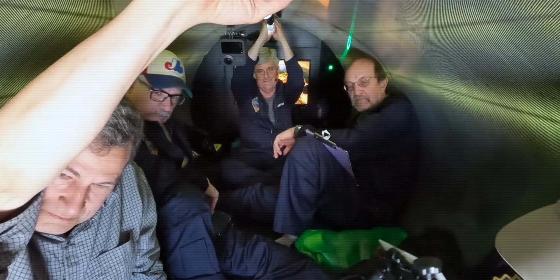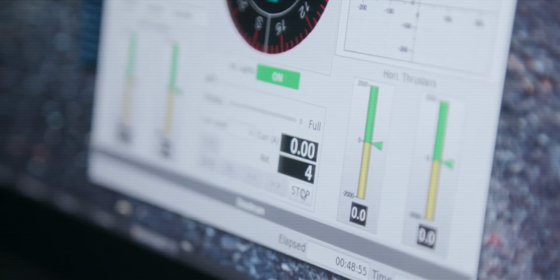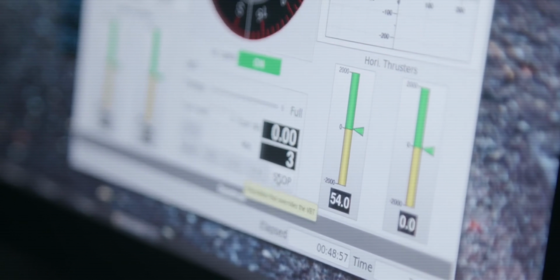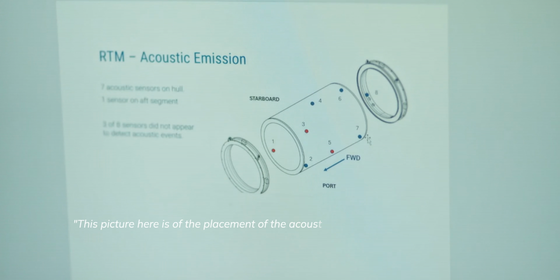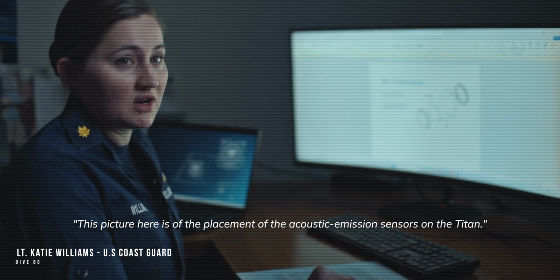The difference was striking. Before Dive 80, Titan's strain closely followed a straight line relationship with depth, indicating the pressure hull was behaving as expected. After Dive 80, that relationship changed. At shallow depths, roughly the upper 500 meters, the strain response became non-linear, while at greater depths, it remained largely unchanged. This picture here is of the placements of the acoustic emission sensors on the Titan.